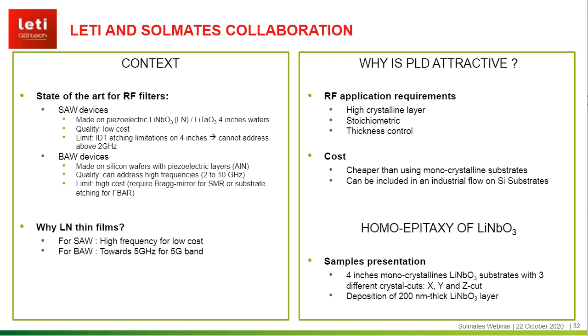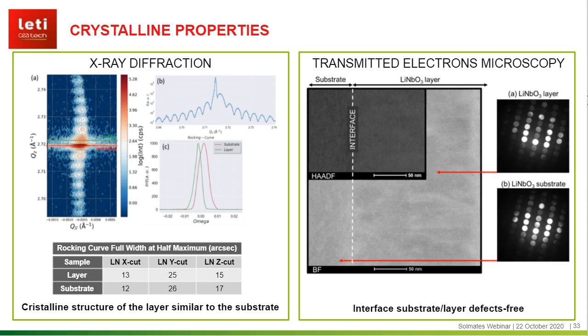This is why we have decided to collaborate with Solmates on the subject and try to perform a homoepitaxy of lithium niobate. This time we used lithium niobate substrates of different crystal cuts and deposited a 200 nanometer thick lithium niobate layer. We wanted to test, in the first place, the quality of the process before further experiments. And the results are promising.